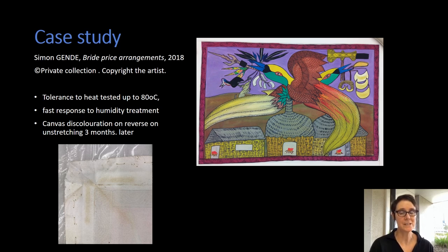The canvas is a plain weave cotton. During stretching, heat tolerance was tested. And again, no visible effect on the priming was noted up to 80 degrees Celsius.